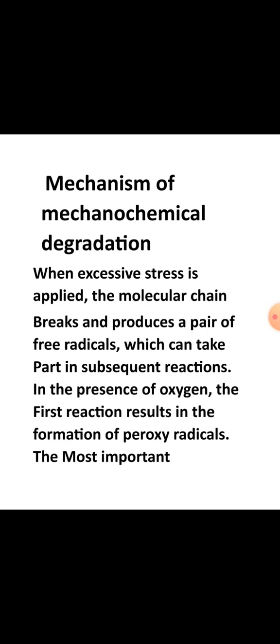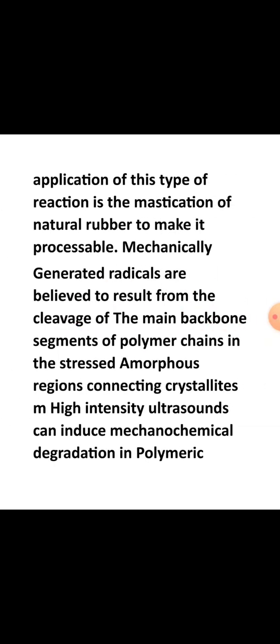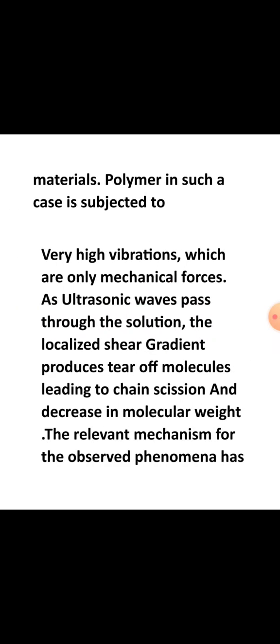Mechanism of mechanochemical degradation. When excessive stress is applied, the molecular chain breaks and produces a pair of free radicals, which can take part in subsequent reactions in the presence of oxygen. The first reaction results in the formation of a peroxy radical. The most important application of this type of reaction is the mastication of natural rubber to make it processable. Mechanically generated radicals are believed to result from the cleavage of the main backbone segment of the polymer chain in the stressed amorphous region connecting crystallites. High intensity ultrasound can induce mechanochemical degradation.